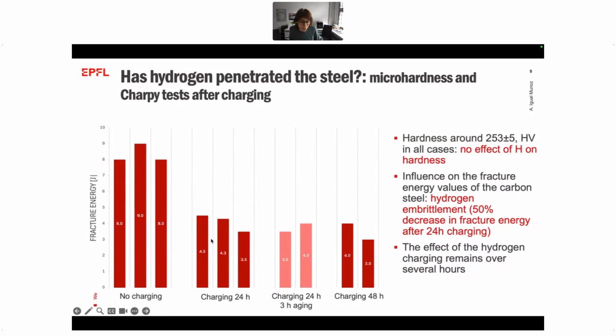Even more, this effect of the hydrogen remained the same over several hours. This is the fracture energy after charging for 24 hours and leaving it in open air for 3 hours. So the decrease in fracture energy didn't change during this period of time. That was good news, because we have a little bit of time to carry out the tribological test, and the effect of hydrogen is still there.